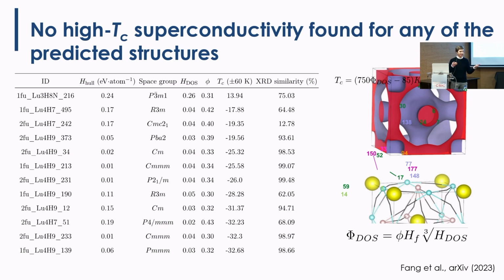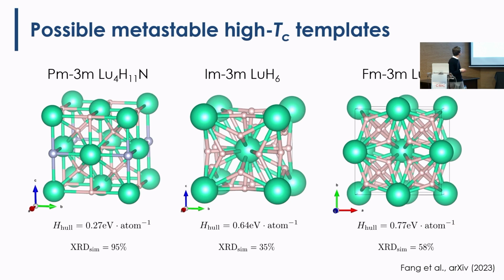We gave them another possibility, another option, okay? And we consider this kind of template, because this is the lutetium H10, the one that gives in lanthanum the high TC of 250 Kelvin, okay? This is very far energetically. It's pretty much 1 electron volt per atom above the lowest energy structure. So it's impossible that this is synthesized experimentally. Also, the X-ray similarity is very low. So it's very different from the X-ray. Okay, so no, cannot be.